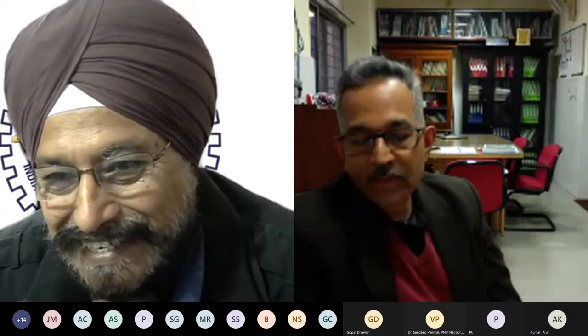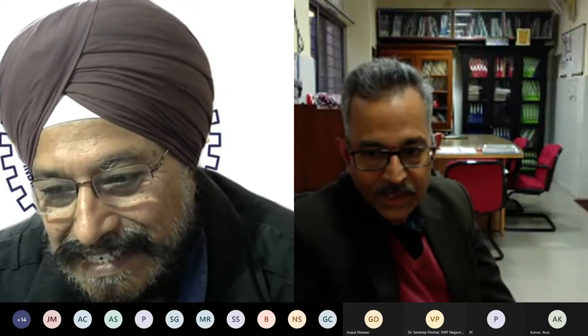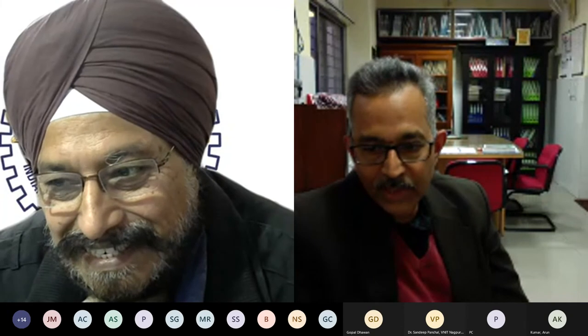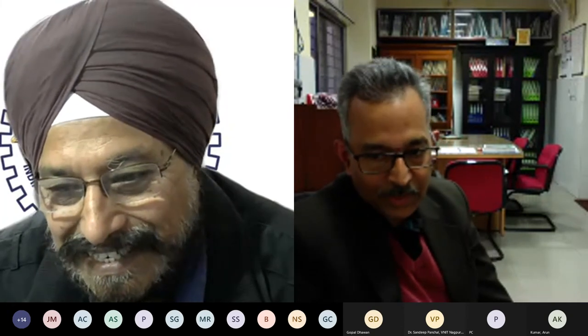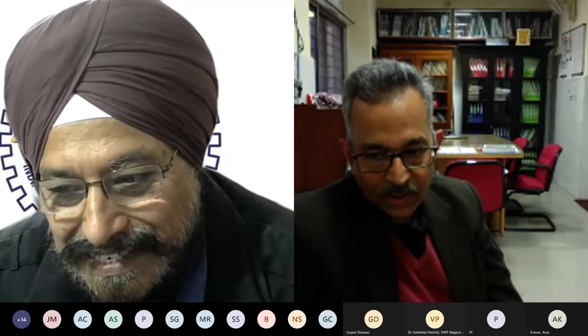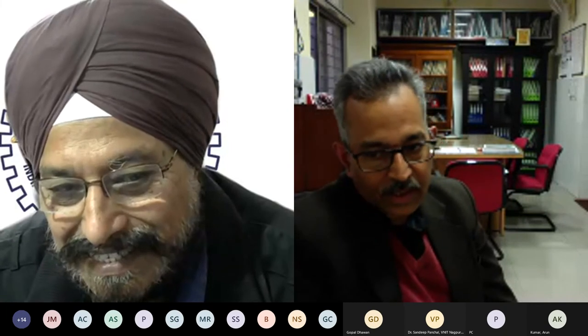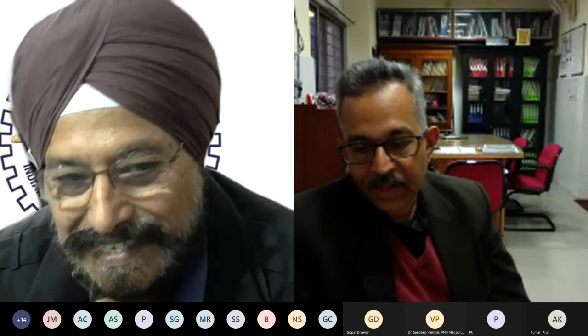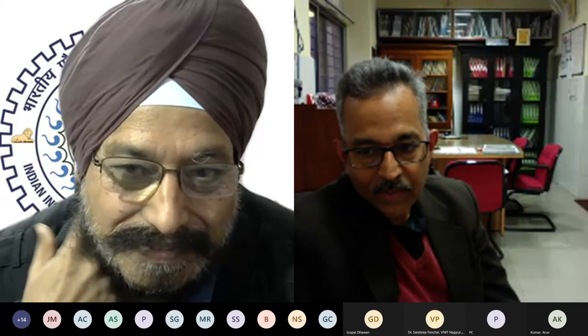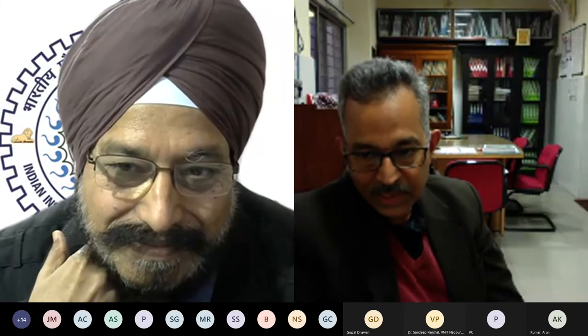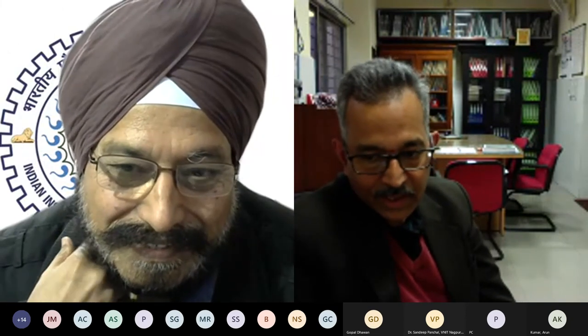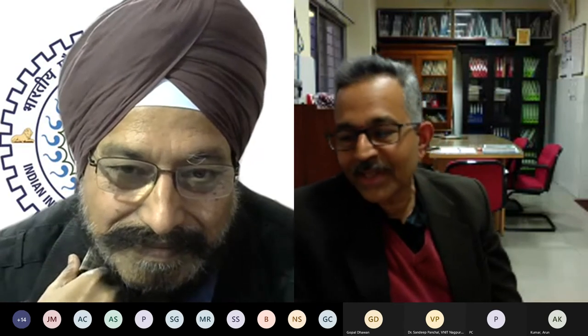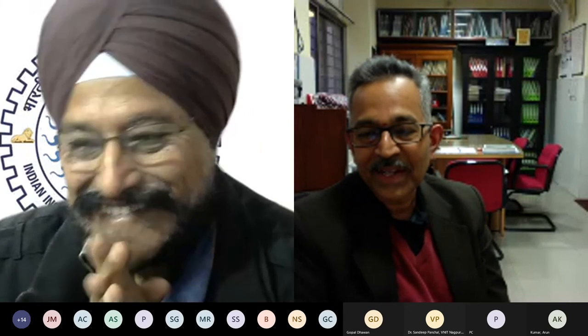Sir, brittleness index is also being defined by UCS by BTS. That is another relation people have proposed, wherein it becomes an index properly without any dimension or unit. So the higher it is, the more brittle it is. That's the kind of definition people have given from a blastability or cuttability point of view. So many brittleness definitions are there, and it needs to be applied as per the conditions.